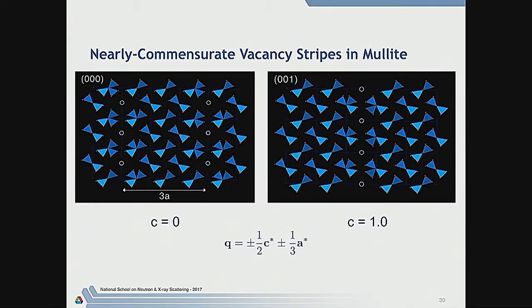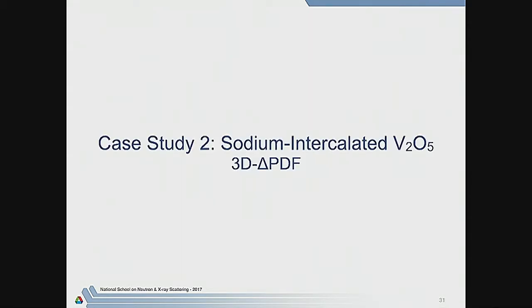So the fact that we have that modulation means that, as I say, there's some sort of modulation of the vacancy concentration, which has a periodicity of about 3 lattice units. This would be the simplest version of that. You have a stripe here, you have a stripe here, 3 lattice units away. And then the next one up in the C equals 1 plane, one plane up, that same stripe will be out of phase. And you can imagine that this might be caused by, for instance, just Coulomb interactions between the vacancies. And it turns out that that is exactly what the ab initio calculations predicted, that you'd have a tendency for the vacancies to line up in these stripes.